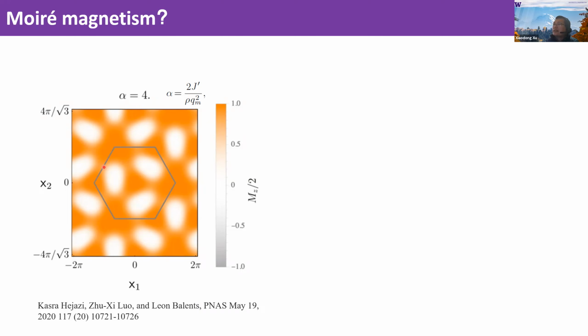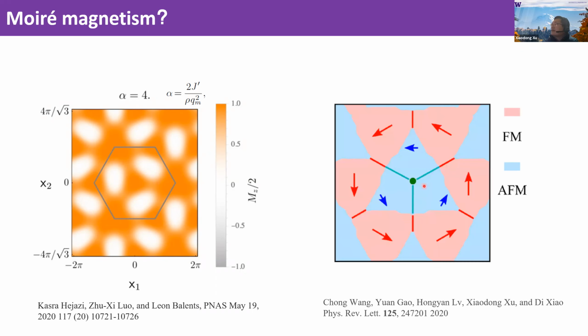Basically, you will see these periodical patterns, right, from AFM to FM. And there's another work from my collaborator. He also calculated very small twist angle chromium triiodide bilayers, and he considered the lattice reconstructions in his models. Then he found, right, this blue, which is AFM, and the red is FM, okay? And then he also sees these magnetic patterns, and at the boundaries, there are magnons, we call them 1D magnons, etc. Okay. So without going into the details, you will see that there are interesting AFM and FM domain patterns in